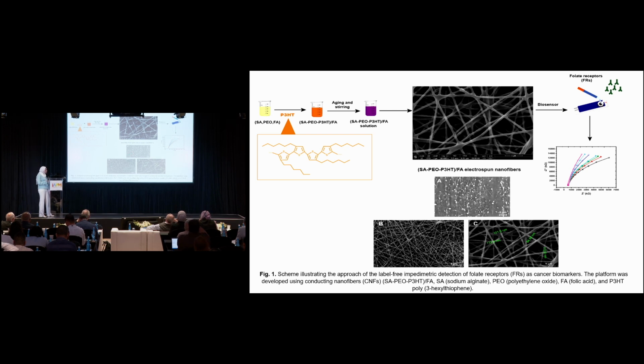When we optimized the ratio of P3HT, it was above 1%. We obtained the bead morphology, which is not recommended for our biosensor. So we started to reduce the amount to less than 1%. We obtained a very homogeneous structure with a smooth surface and a small diameter of around 84 nanometers, which confirmed a large surface area.